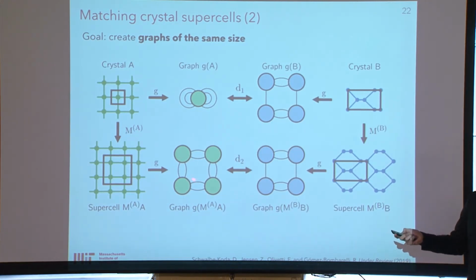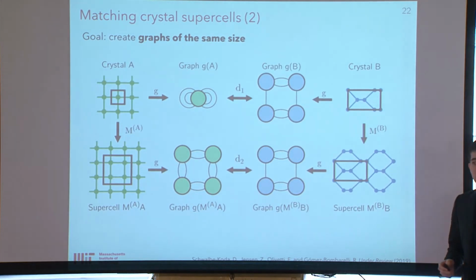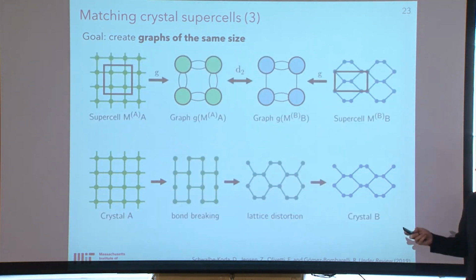Here, compare, for example, the graph of supercell A with the graph of supercell B. We see that the only difference between those two is that graph A has 2 extra edges here. Interpreting these results from the transformations perspective, it means that to convert crystal A to crystal B, we first have to break these 2 extra bonds, and then distort the lattice in a diffusionless-like transformation to achieve crystal B.